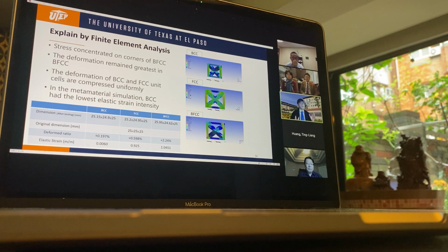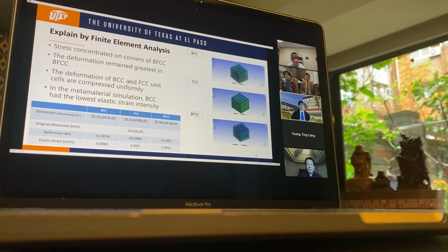There is no significant difference between the FCC and BCC structure when under loading. However, when under loading, the stress will focus on the corner of the unit cell of BFCC. We consider that this is the reason that BFCC has a distorted deformation. Then we use the same parameters to do a simulation for the metamaterial structure.